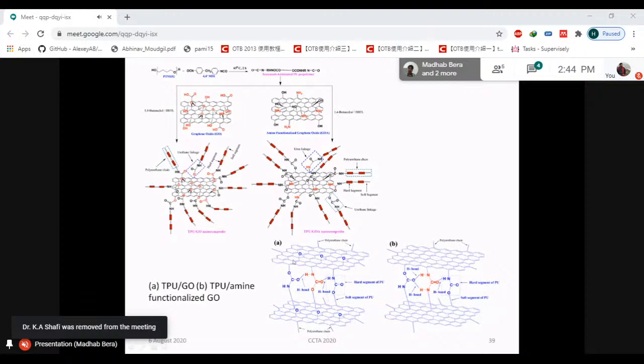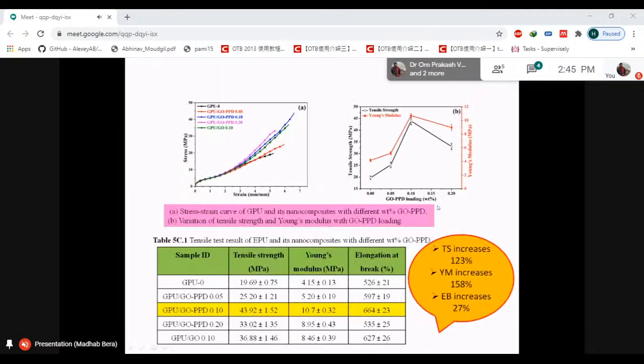Now this is the interactions and the chemical structure that is responsible for this kind of improvement. In case of GO, if we look at the structure in figure A, you can see that in case of graphene oxide, there is only one hydrogen bonding interaction with the adjacent urethane linkage. But if we use amine functionalized GO, then there will be bidentate hydrogen bonding interactions, and because of these bidentate hydrogen bonding interactions, the mechanical properties improve drastically.